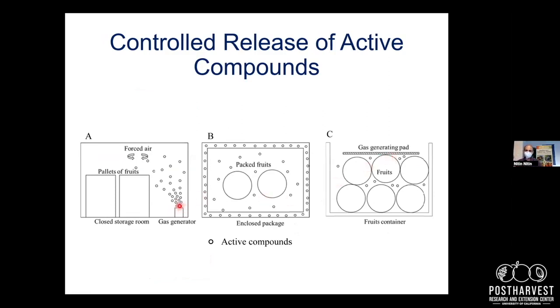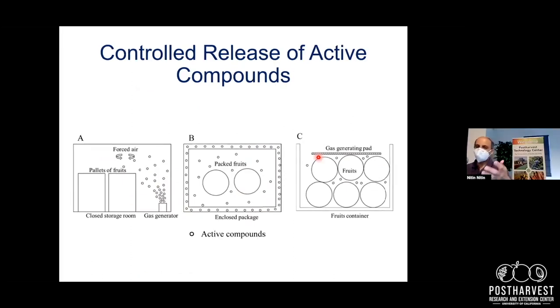For example, in one case, you could have a gas generator that would interact with the pallet of fruits to distribute this active agent. You could have a packaging material where this is coated on the surface, and this material would be released over a period of time to maintain the activity in the packaged environment. Or what has become very common in the industry is these gas generating pads, functional pads that could be used to control the distribution of the gaseous or volatiles in this case. And the dots indicate here the active compound that's being released.